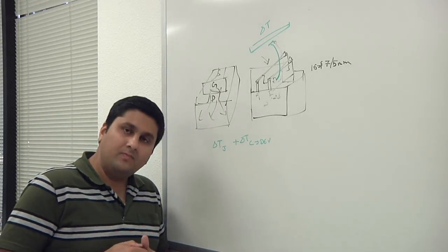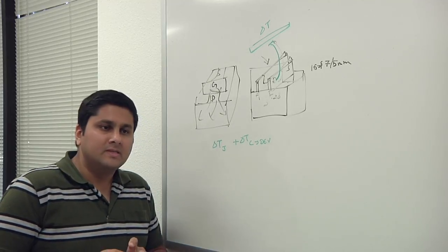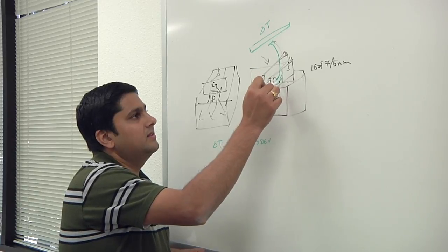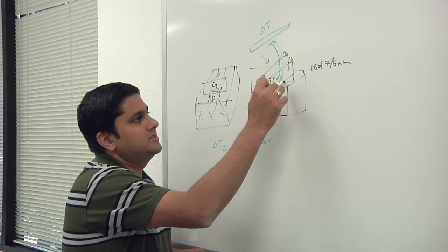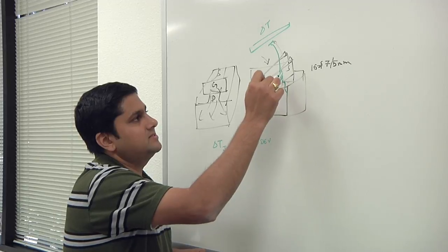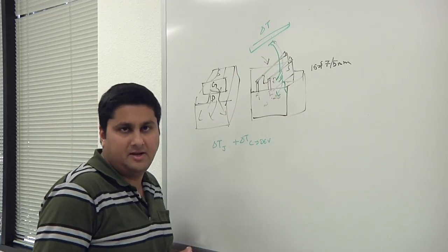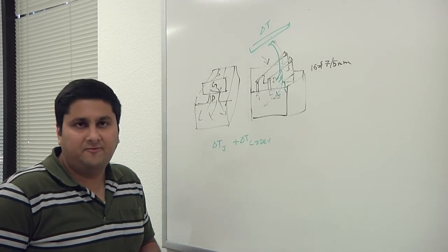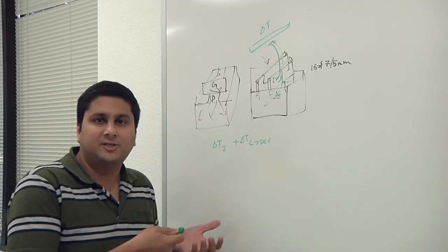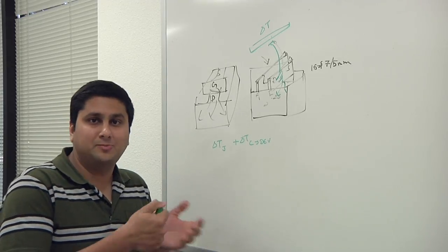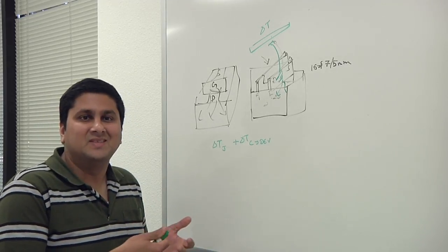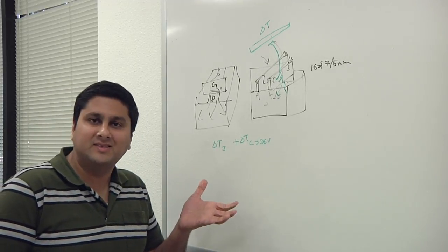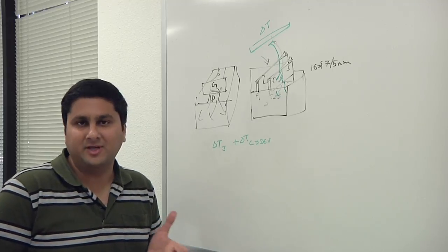We've been hearing about self-heating for a while. What is that? So self-heating essentially is the heating on the channel that cannot be dissipated through the substrate. So the heating of these transistors that gets coupled through to the interconnects. That is the effect. And what's the impact of that? Impact is basically lifetime. So as everybody knows, the temperature is having an inverse exponential dependence on the lifetime. So as your temperature increases, your lifetime goes down. Maybe with every 5 degrees Celsius increase in the temperature, your lifetime degrades by 30%.